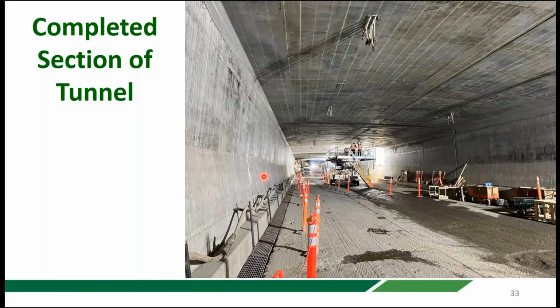Obviously, if they went in and removed all of the chloride contaminated concrete, they wouldn't need to do any galvanic or impressed current cathodic protection. But based on my discussions with the engineers, the issue was if they removed that much concrete, the tunnel section wasn't structurally stable anymore, and so they had a huge structural problem to deal with.